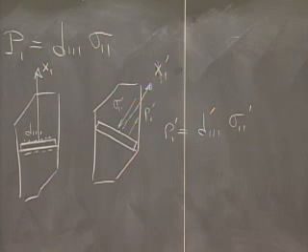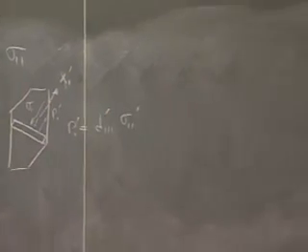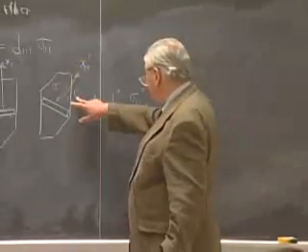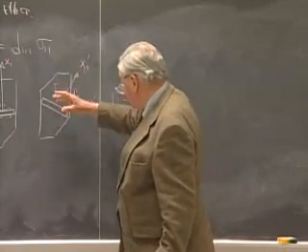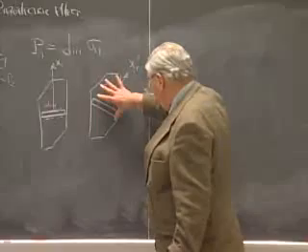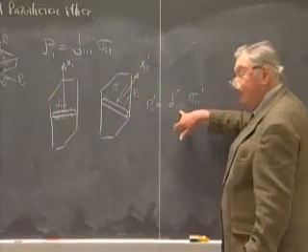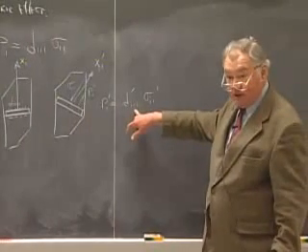It's going to change all of the piezoelectric matrix elements, but we're looking at an effect in a sample that is deliberately prepared such that we will measure only the surface charge given by P1 prime, and therefore the way in which the properties of this plate change as we vary the way in which we've sliced it out of the single crystal is going to be simply the variation of D111 prime with direction.